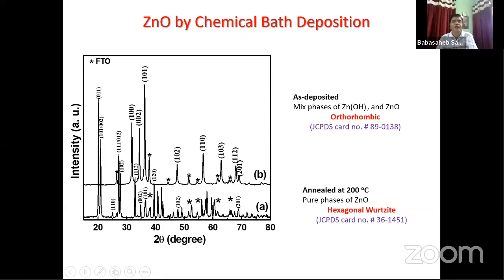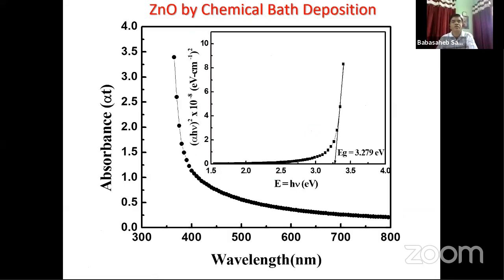Then one criterion for the dye-sensitized solar cell is that your film should have a wide band gap. In order to test the wide band gap of that zinc oxide, we took absorption against wavelength and calculated the band gap value by plotting alpha h nu squared versus h nu, where we can see that the band gap is more than 3 electron volts. It means whatever visible part of the solar spectrum is there, it can pass through this zinc oxide.